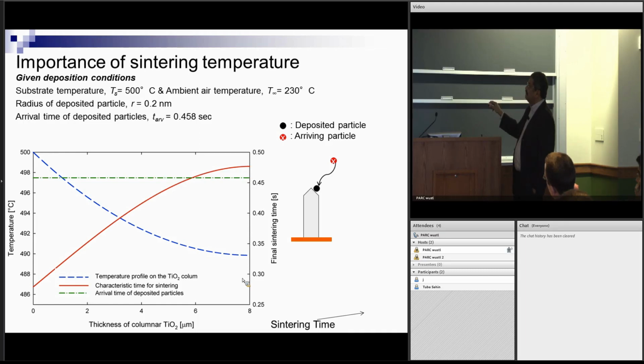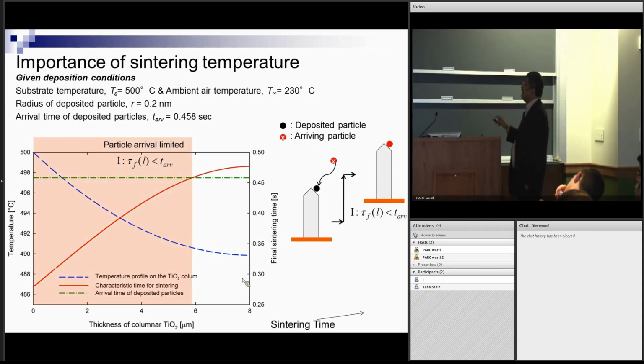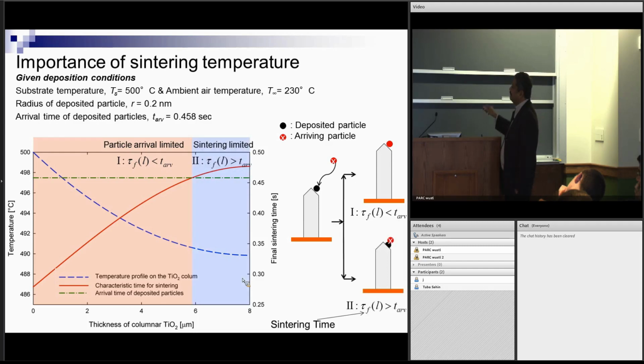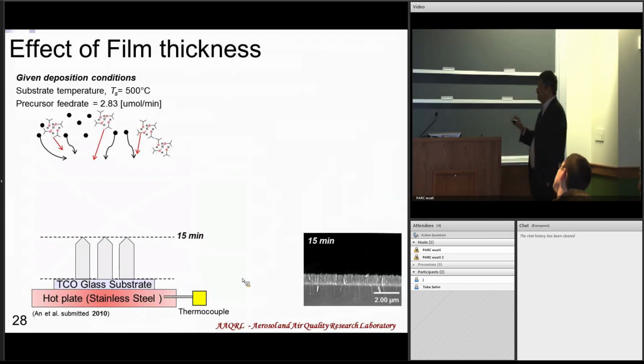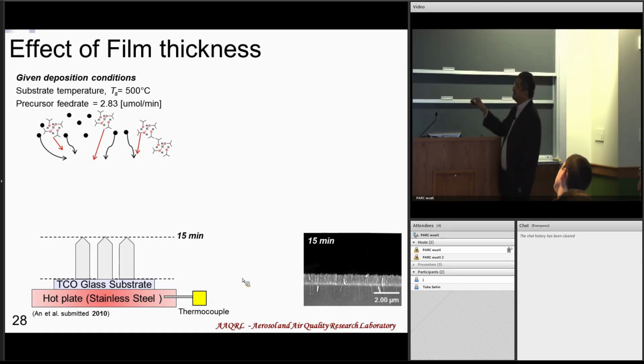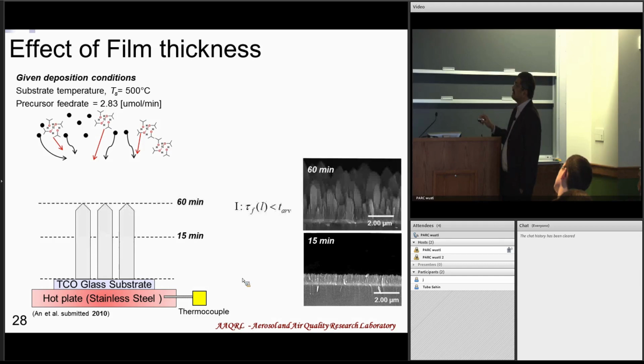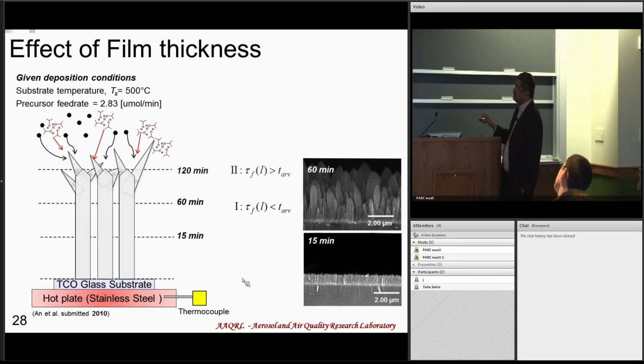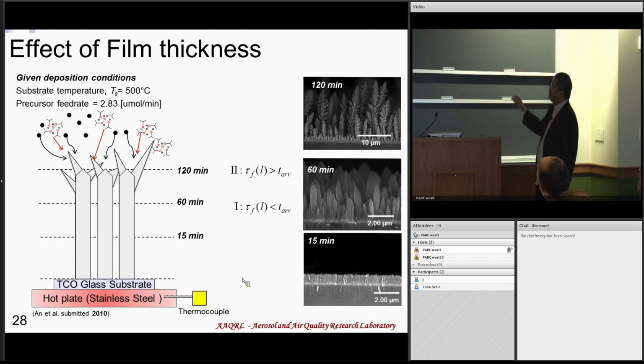So the next arriving, before this can sinter out, the next particle has already arrived there, and you can see that if the sintering time is much smaller than the arriving time, it's going to become one big blob. If it is not, it's going to start growing there, and you begin to see these structures. Again, I'll just walk you through this. This is the precursor coming. I'm forming my single crystal structures. I can do it for about 60 minutes, but then it's become long enough, it cools down, and I start growing branches. So instead of growing single columns, I can get, you can't see this too well, but maybe in the next picture, you can see I can get these branched structures.